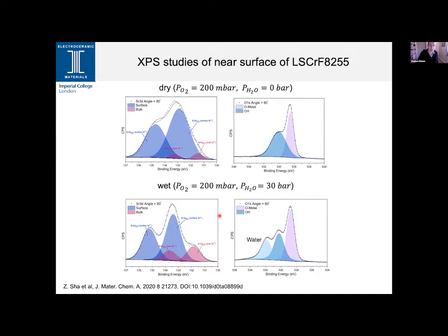So we turned to X-ray photoelectron spectroscopy in both the dry and wet samples. So ex situ measurements on identically treated samples. We focused on the strontium 3d and the oxygen 1s species. And we can see that in the dry atmosphere, we have these oxygen 1s species corresponding to the oxygen metal and some OH. In the wet atmosphere, we have an additional feature corresponding to water, and we can also see a difference between the surface and bulk strontium signals in that XPS. And this is looking at the angle resolved. So this is a very shallow takeoff angle.